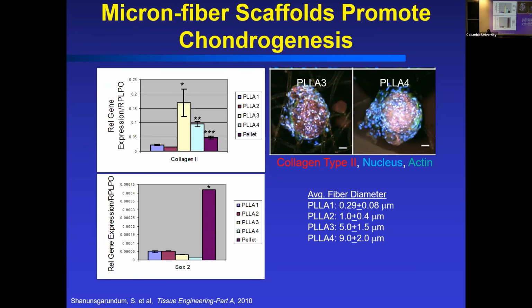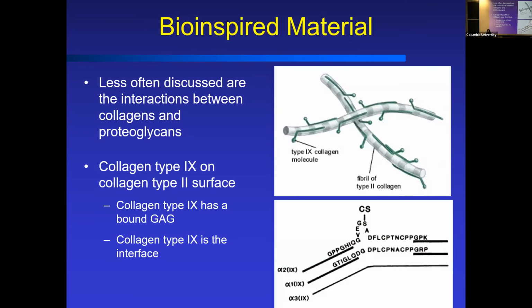So they still need to have some adhesion to the scaffold itself, but they do need to be able to have cell-cell interaction. So shown here, these aggregates on the far right, those are really only seen or promoted on the materials that had the larger micron sized fibers. So 5 and 10 microns in size, that PLLA3, PLLA4.